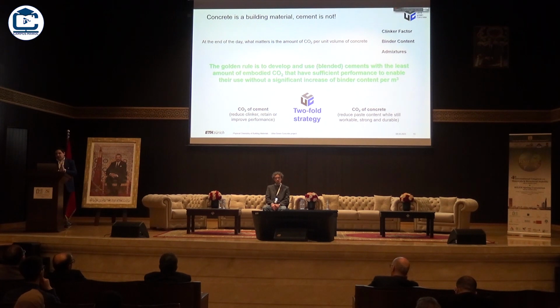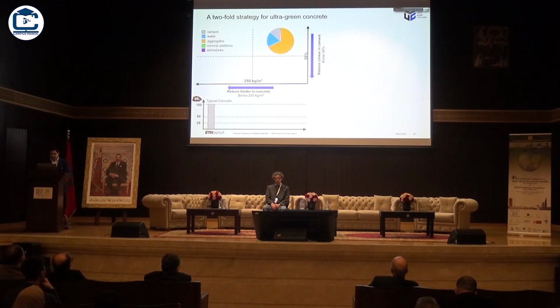And this is what in this Altering Concrete project we summarize in this concept as the twofold strategy, where we look at the CO2 of cement, which of course is related to the clinker factor, but more importantly, we look at the CO2 of concrete, which is related to a reduction of the binder volume per cubic meter.